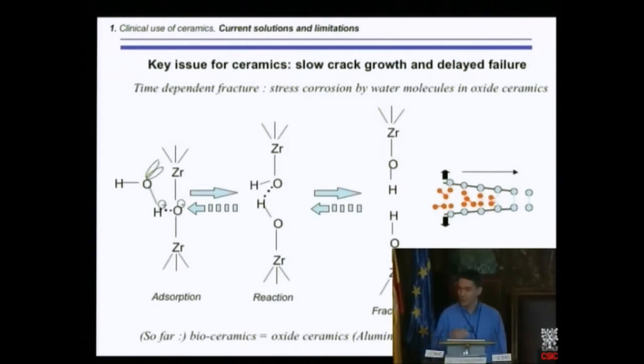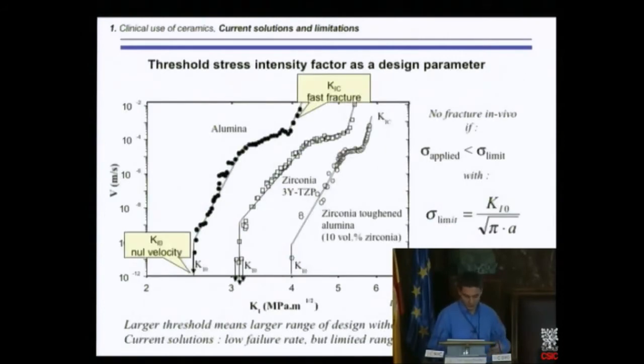That's another important issue. I won't go again into details in the process, but we know that ceramics are sensitive to slow crack growth, so we need ceramics with a higher resistance to slow crack growth. If we take biomedical ceramics, unfortunately, they are all oxide ceramics. Alumina, zirconia, hydroxyapatite, tricalcium phosphate, all calcium phosphate-based ceramics are also oxide ceramics. So we expect that so far, all bioceramics are intrinsically sensitive to slow crack growth, especially stress corrosion by water molecules.